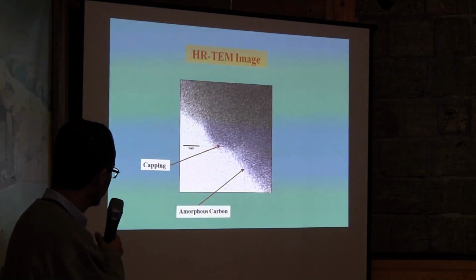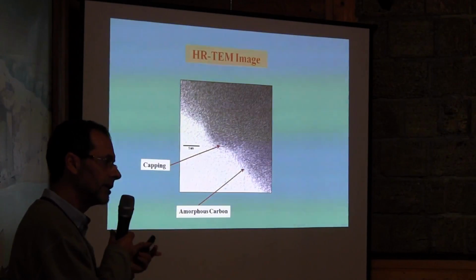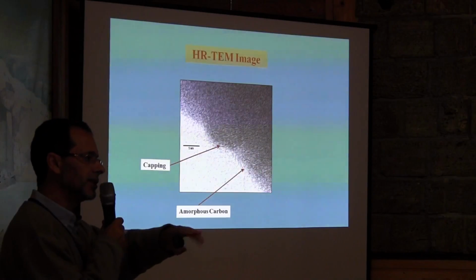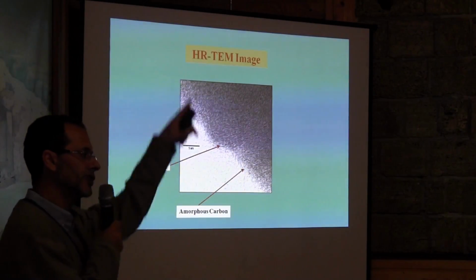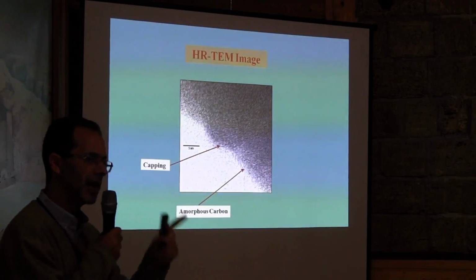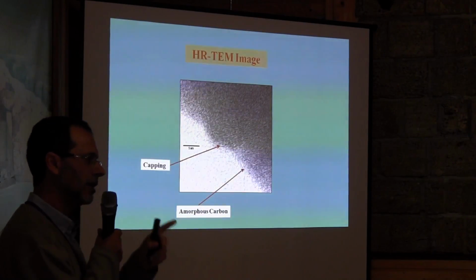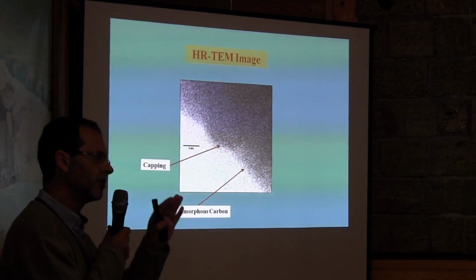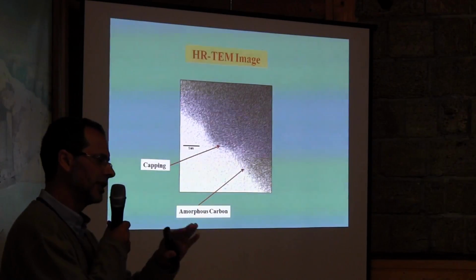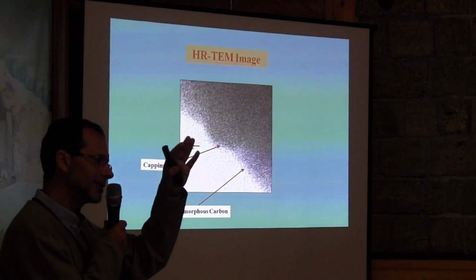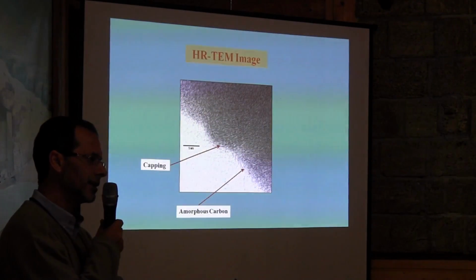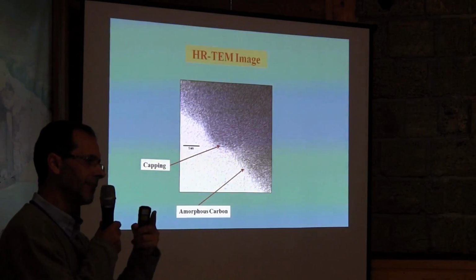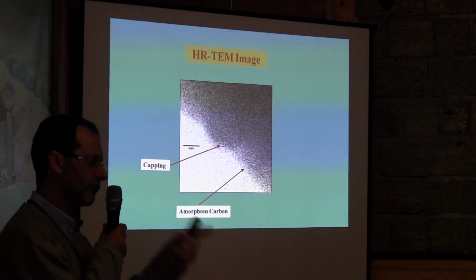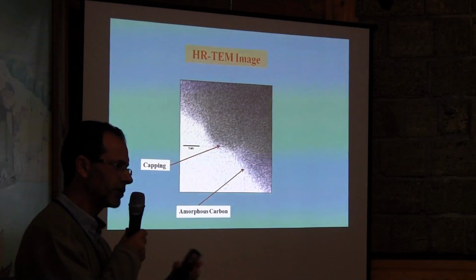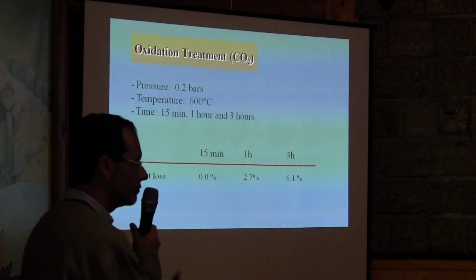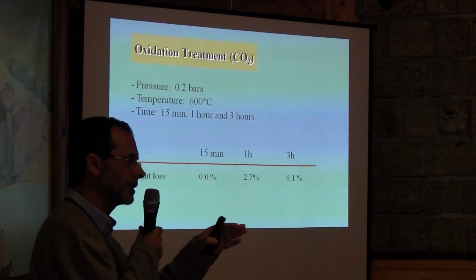Second thing, we form amorphous carbon. I did SAD again, because if you make a selected area diffraction, you can see a continuous ring. If you have a continuous ring, that means you have amorphous carbon on the edge of your tubes. This is very common for carbon nanostructures, especially nanotubes, multi-wall or single wall. In some cases you always have an amorphous layer on the edges. So that's why, to make functional carbon nanotubes, people need to make surface treatment, either using reflux treatment or other methods.